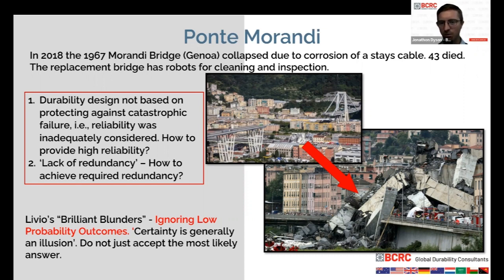They obviously looked a lot at why this occurred, and they decided the replacement bridge should have robots for cleaning and inspection at regular intervals. One of the reasons the collapse happened was that the durability design of the bridge was not based on protecting against catastrophic failure. In other words, the reliability was inadequately considered.